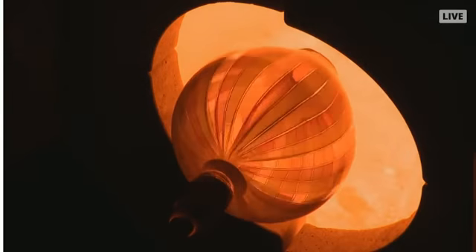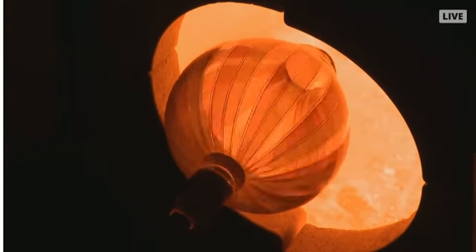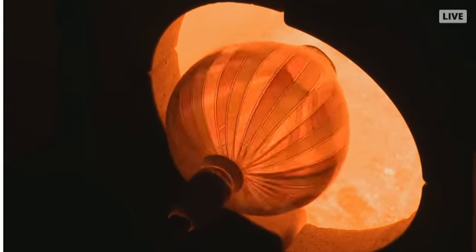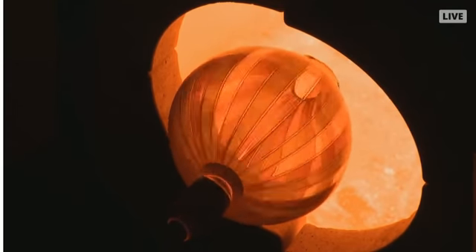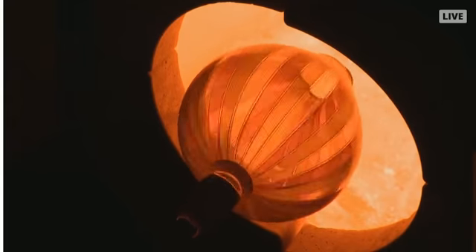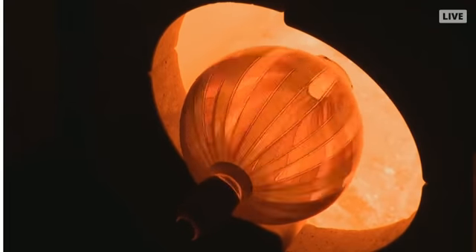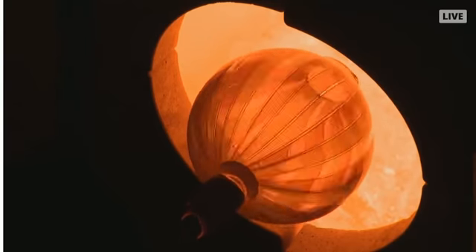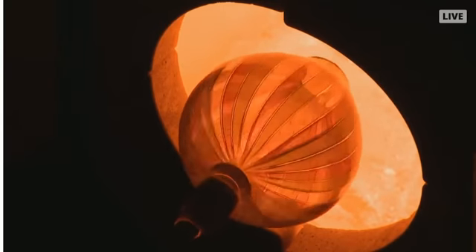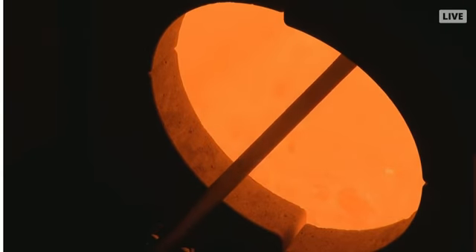If something is going to go wrong, it usually happens right there. What you have to do is get the glass cold enough that it will actually break. So you have to cool the glass down into a really dangerous temperature range where it will snap. If the glass is too hot, it won't break. It's like trying to break chewing gum. So she had to cool that right down to the point where the whole thing could shatter, right down to about 1,000 degrees. But she had a nice tight constriction in there, and she put a little bit of water on it and gave the pipe a tap, and it broke right around that constriction.